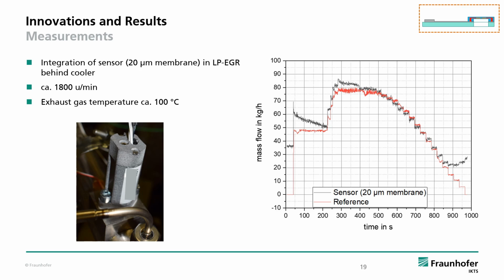Slight differences are seen in the absolute mass flow value. At the first step at about 46 kg per hour, the black curve is drifting away. The smaller steps show no drifting and have stable values, but different to the reference one. That could be a calibration error. The drifting in the first step has to be analyzed further, to see if the sensor is really drifting or the mass flow really decreases.